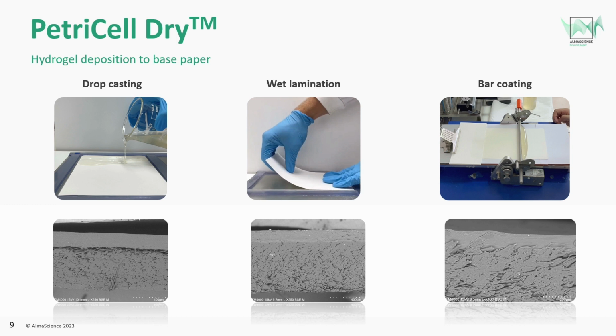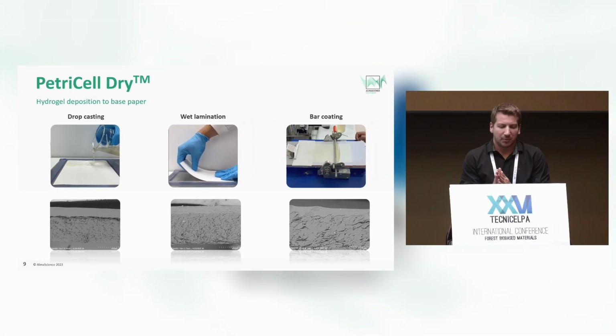Second, we kind of call a wet lamination. It's not really a wet lamination, but we have the reverse drop casting where the formulation is on the mold and we deposit the paper on top. Dry it a little bit and apply a little bit of pressure to make them stick together.